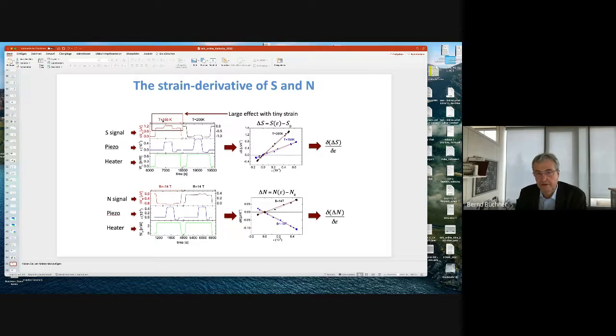And this is at one temperature. You see, this is, let's say, the signal which we detect. If you do that at higher temperatures, the thermopower is negative, but the strain effect is still positive. And then you can plot the strain effect, so this delta S, as a function of the size of a strain, get a straight line, and again get something like a susceptibility. So this delta thermopower versus delta epsilon.